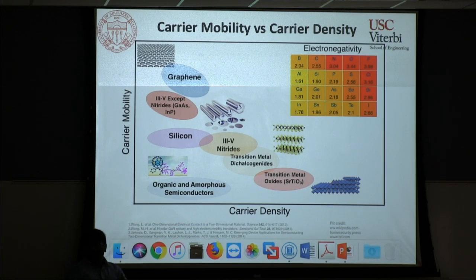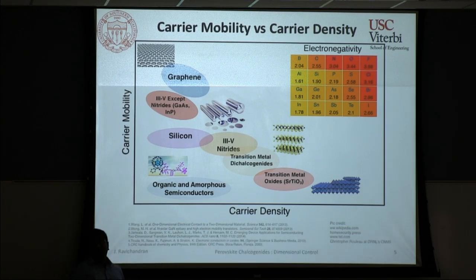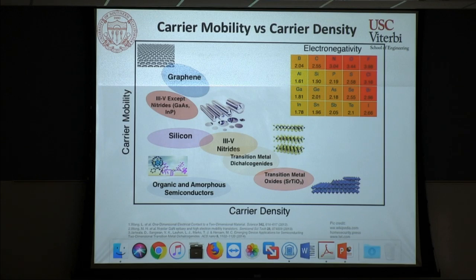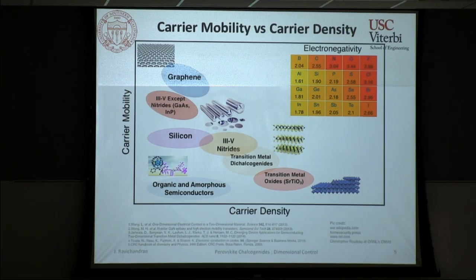So this is a mechanism by which you can go for a material that has sulfur and selenium instead of oxygen in this framework, where you can have much lower electronegativity difference and hence much better carrier mobility in your system. So that's our general prediction, and it also holds true because transition metal dichalcogenides do have much higher mobility than oxides. Okay, so our question was, can we find some material with slightly better carrier mobility with high carrier density? And we think transition metal perovskite chalcogenides is a candidate system.